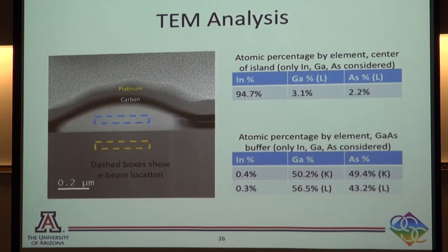This is the TEM analysis of how the surface looks. We did a lot of TEM, and this is one of the examples. Indeed, it's 94% indium, and this is just a touch of indium in the buffer, a point of 0.4, so for all practical purposes, it's indium.